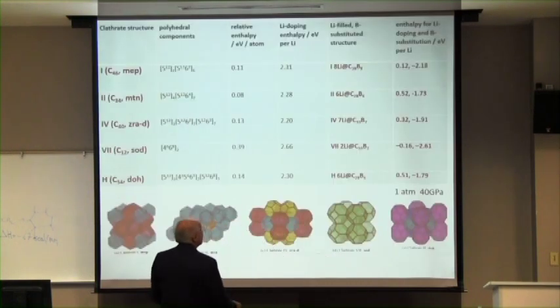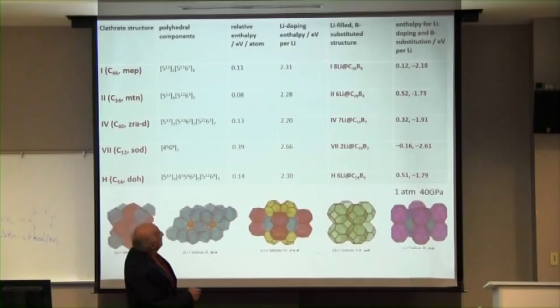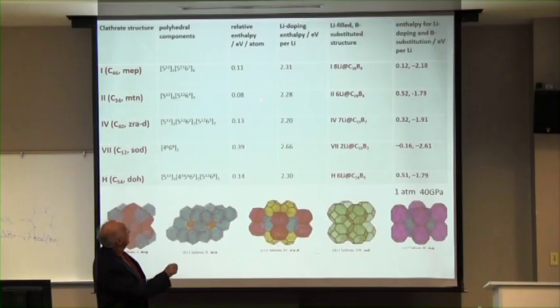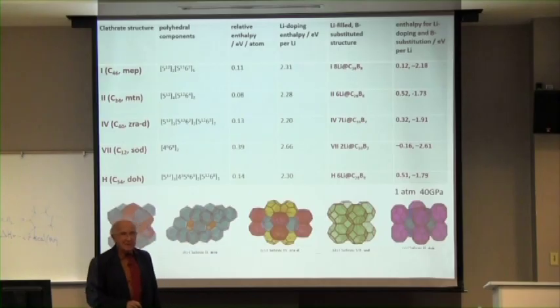So here is the end of a story in this paper, and that is, here were the energies of the 5 clathrates with nothing in the middle. When you stuffed them with lithium atoms, I told you there was no room for them, but theoreticians can do tortures on molecules. There's no problem. We stick them in, we calculate, and the molecule tells us it's 2.3 eV per lithium higher in energy. It doesn't like it. So then we put in 8 lithiums in the middle, but put also 8 borons in the framework, and the electron jumps from the lithium to the boron.